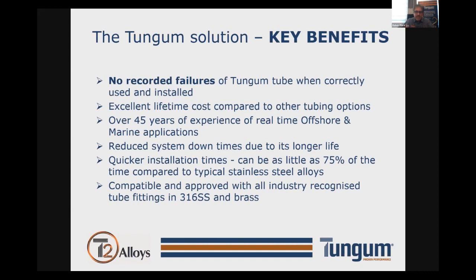The other benefit is that connections, you can use a typical 316 stainless steel fitting. This is what many people ask the question. I can't use a 316 tube, but I can use a 316 fitting. Yes, that is correct. And the reason being is that if you look at the galvanic compatibility between 316 and Tungum, they're almost identical. In fact, Tungum is slightly anodic, which means that the overall larger surface area of Tungum is actually protecting that very small connection between the 316 fitting and Tungum. Therefore, the reaction never takes place, and the fitting is somewhat protected by the tubing itself.